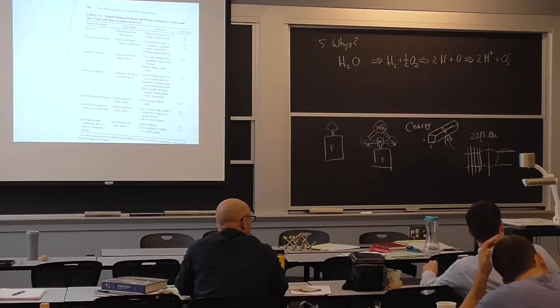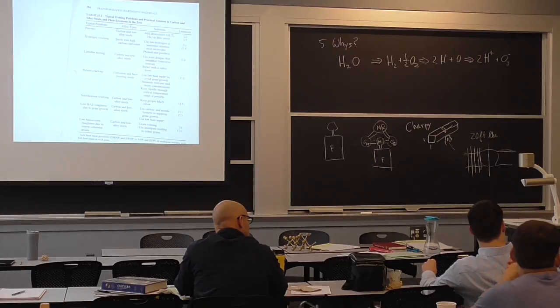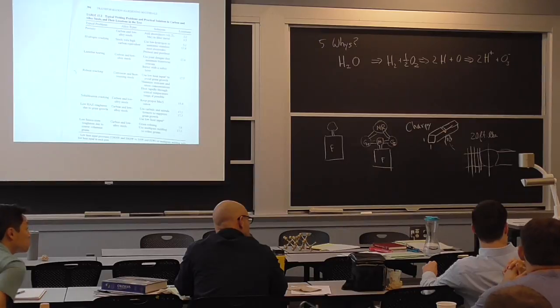And after they did that, maybe 2/3 of the ones that didn't pass the last time, 8, 18, or 19, would now pass at 20 or 21 or 22 or whatever. And then some of those that didn't pass, the 10% that still didn't pass, they would put through a second renormalization and see if they could get it to pass, and some of those would pass, some of them wouldn't. They'd scrap the ones that, after 3 tries, didn't. How many times are you going to put it through there, okay? Now, if they were Japanese, they would just lower the sulfur, okay?